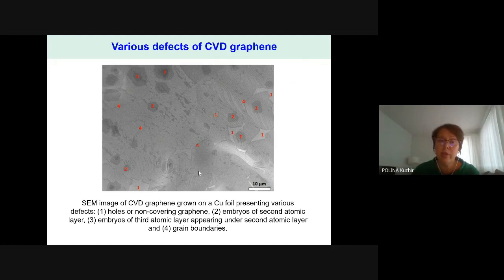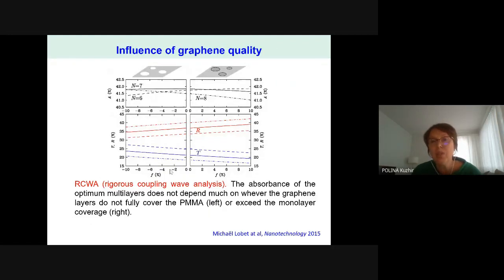Even if we deal with not very high quality graphene with a lot of defects, like embryos of the next layer or holes typical of CVD graphene, our electromagnetic response won't feel the difference when the fraction of defects is less than 10%, or even up to 20%. So if you have decent quality graphene with some holes here and there, or embryos of new layers as normally happens with CVD graphene, you shouldn't worry, because the electromagnetic response stays the same.